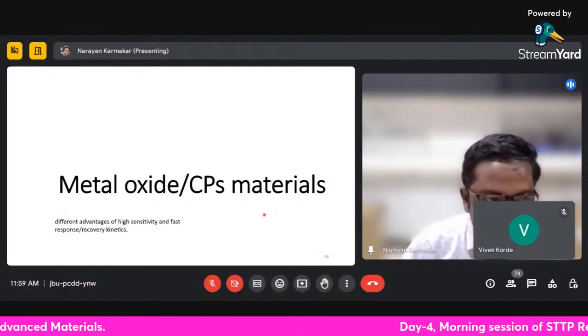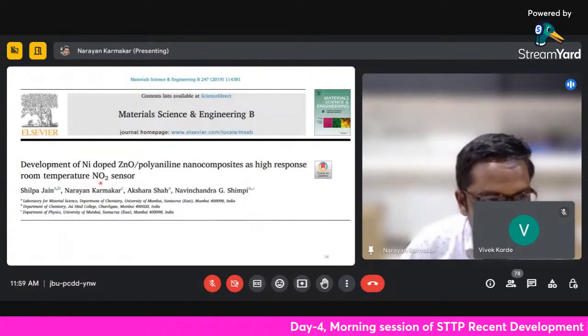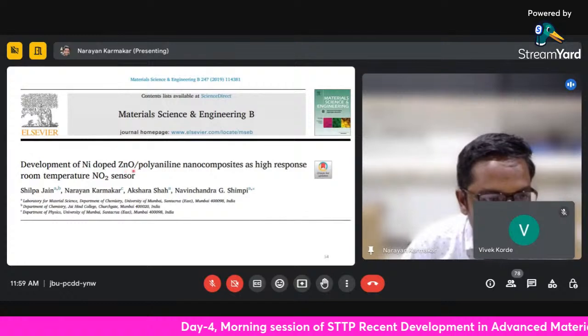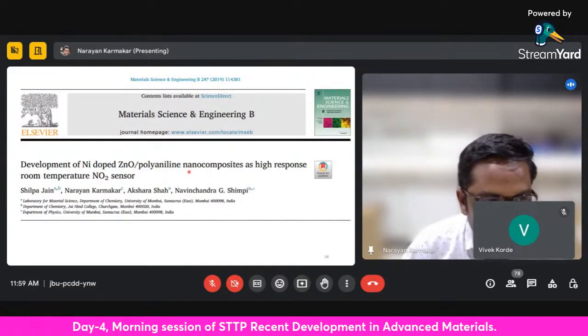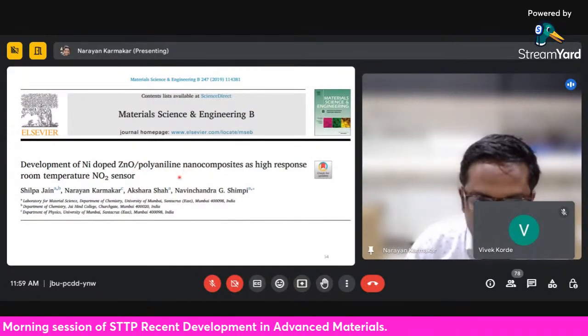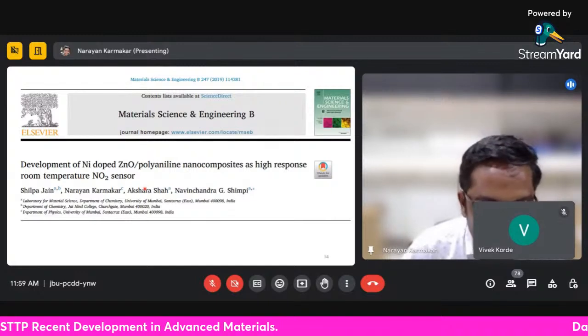So the next step we did is this: we synthesized a nickel-doped ZnO polyaniline nanocomposite, and we make use of it for the detection of NO2 gas.